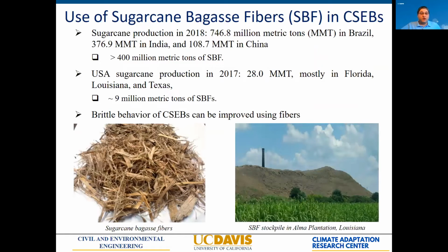Then we wanted to work on the brittleness and the flexural strength. And so we used another locally available material, in particular sugarcane bagasse fibers, which are a byproduct of sugarcane production. There are more than 9 million metric tons of fibers produced each year in Louisiana, Texas, and Florida mainly. About half of this material is burned to produce the electricity used inside the sugarcane mills. The other half is stockpiled and is actually a fire hazard that needs to be dealt with. So we were hitting really two things at once, improving our material and also finding a beneficial use for a waste material.